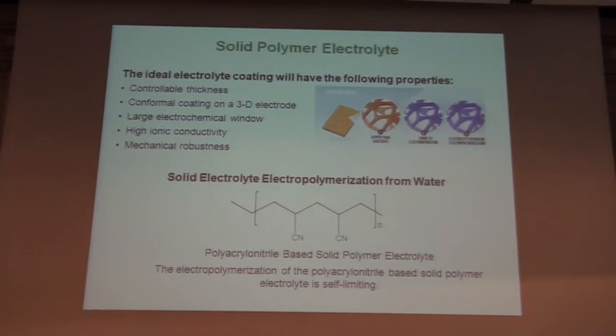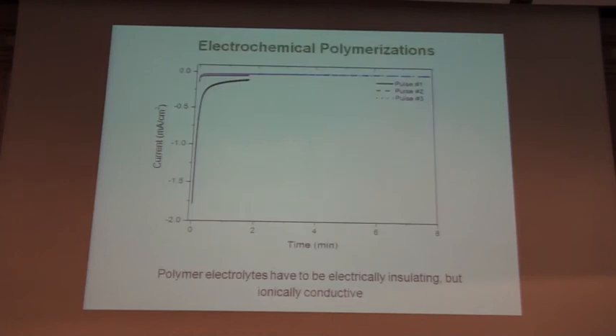But basically what we had to do was develop the methods for electrochemically polymerizing mixtures of monomers that would each have the physical properties that were needed to result in this polymer electrolyte. We use electrochemical polymerization because, remember, the polymer has to be electrically insulating. So the idea is that as you polymerize the material and it coats your electrode, it will turn itself off once you've completely coated. So this data demonstrates that. This is a current density as a function of time. In the first pulse of the electrochemistry, you get initial polymerization on the surface, which reaches a diffusion limited range. Then you let the solution rest. You pulse a second time. You see the current density is much lower because most of the electrode's coated, and in this way we can make sure it's well coated.